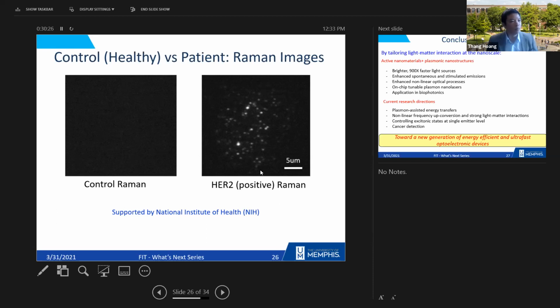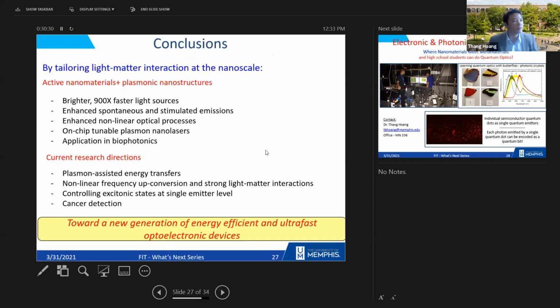As I have only 30 minutes, I would like to jump to the conclusions. Basically, what we do is tailor the light-matter interaction at the nanoscale. In this case, we combine active nanomaterials with plasmonic nanostructures. We demonstrate a very fast, very strong light source, enhanced spontaneous emission and stimulated emission, which is the lasing that I showed before, and enhanced nonlinear optical processes. One example was second harmonic generation, and we saw an on-chip tunable laser, and also an application in biophotonics, using plasmonic nanoparticles to detect cancer.